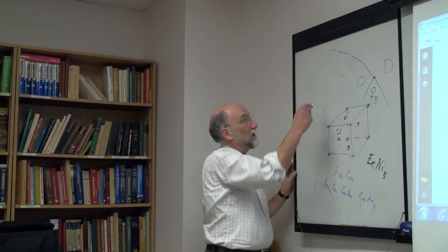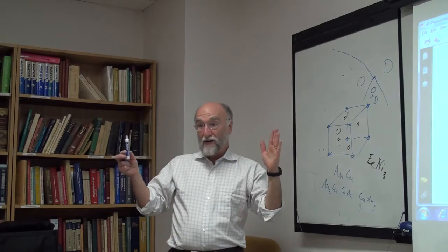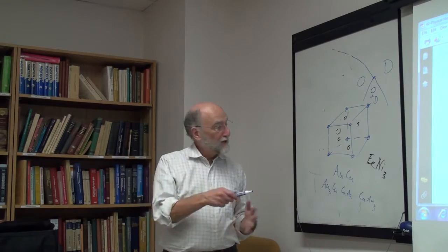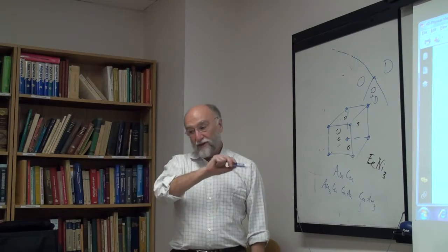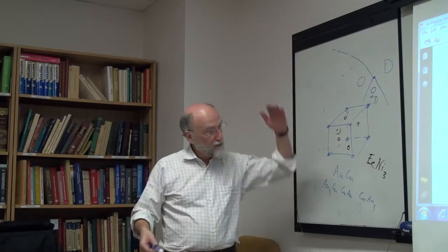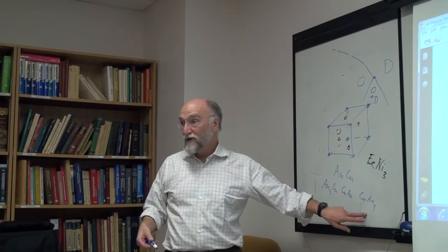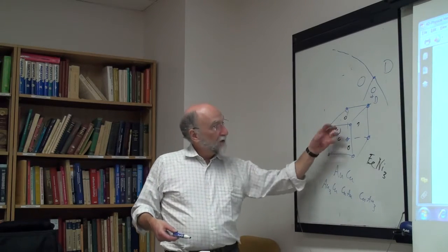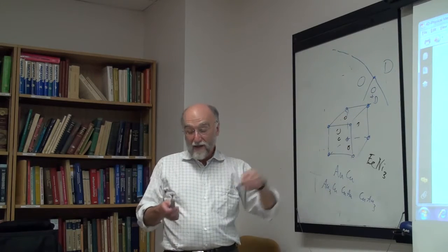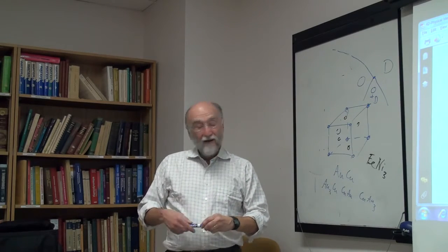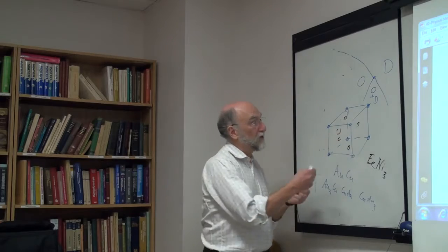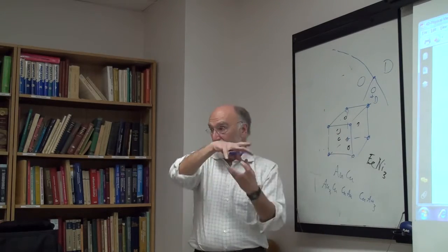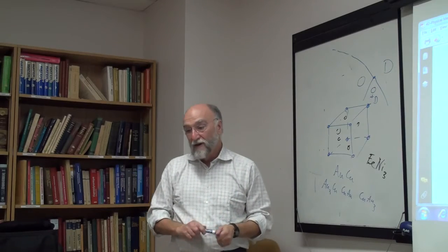Just the way we treat miscibility gaps as one phase, even though it separates, what I mean is one Gibbs energy expression. One Gibbs energy expression has to give, at high temperature, the disordered structure, but at lower temperatures has to give you three separate structures. So you've got to take into account all the ways that these things can interact, and you can't just work on pairs, you have to talk about at least quadruplets, or groups of 4 or 5 or 10 atoms, because you have different geometrical ways of putting these things together.